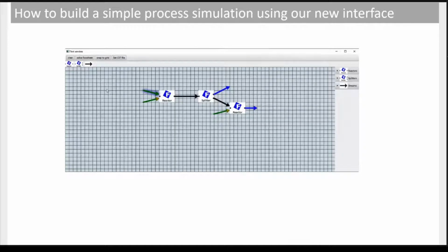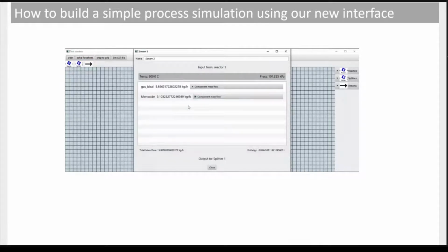So you can do that. And we're going to analyze the result again. So you can start by looking at the intermediate output stream there. And what we can notice here is the fact that we're not producing any more iron. So the FCC phase is gone. Therefore, we don't have enough reducing gas to bring iron to its metallic state.